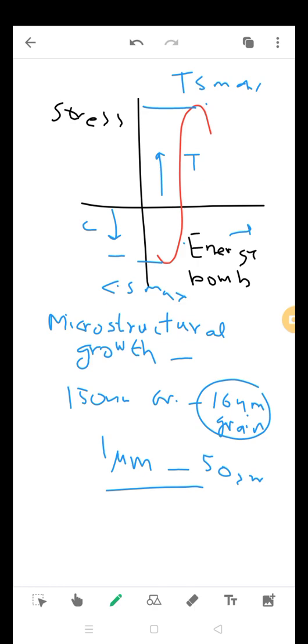And as we have already told you, higher tensile stress may cause film failure, and compressive stress may also cause film failure. So this is the point after which the film actually starts to weaken, both in the case of tensile and compressive. And this tensile stress maximum, this TS max, give the name as tensile stress max, for physical vapor deposition films.